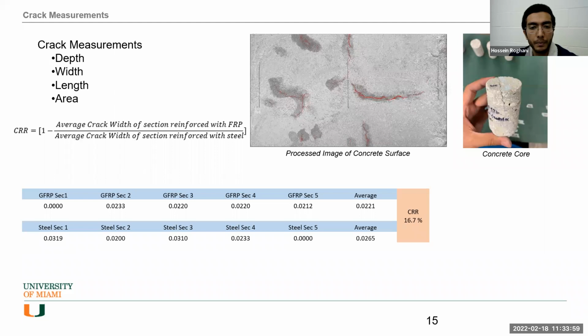And in addition, we had some cores to make sure that the reinforcement is engaged, because if you have just some superficial cracks, you cannot say that it's because of the effect of the rebars. The rebars are doing very well, so we have smaller cracks. But no, we should see the penetration of the cracks and make sure that the rebars are engaged.